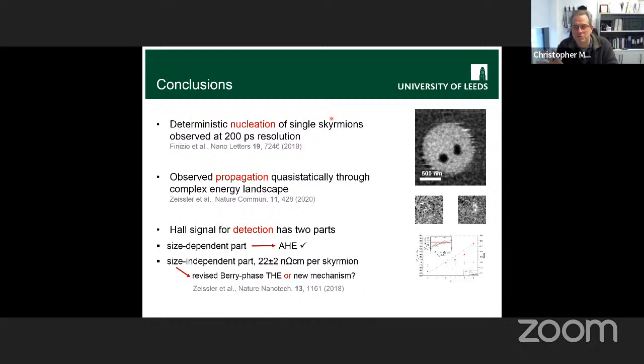All of those images were taken at zero field after we'd applied the pulse, when everything is relaxed and stabilized, and we can see that we can stabilize skyrmions of different sizes. One of those sizes is probably the natural one. The model we have in mind is that as you're injecting your current pulse, you create this bit of reverse magnetization, and then you're inflating it like a bubble.